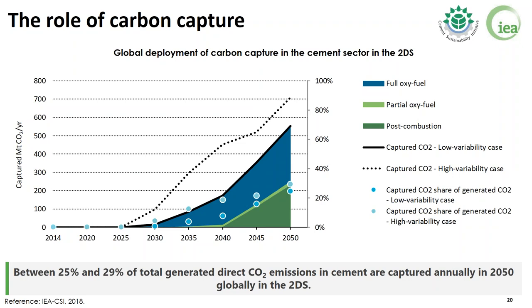And then you see that starting from 2035-2040, also the partial post-combustion technology will start delivering results. Indeed, overall expectations are that in 2050, the range between 25% and 29% of generated CO2 emissions will be captured.